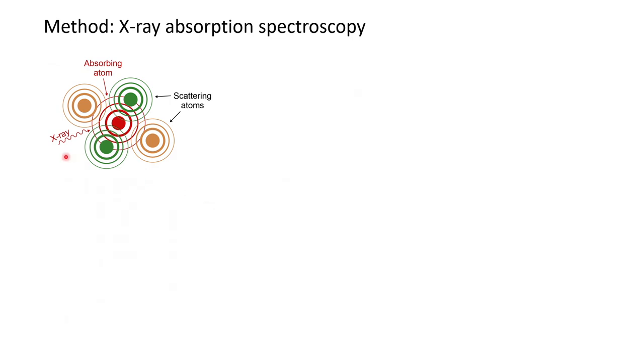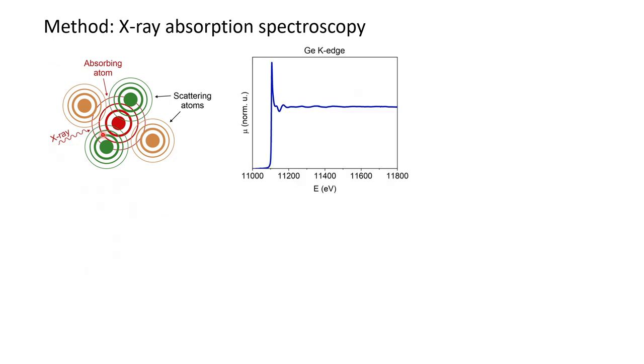So essentially what we are measuring is the absorbance of incoming X-ray beams as we tune the energy of these X-rays. This is the type of data that we usually receive. It has the edge, which tells us which element we are looking at. In this case, we are looking at the germanium edge. And then after the edge, we have these post-edge irregularities, which are constructive or destructive interference of X-rays as they scatter out of different atoms.